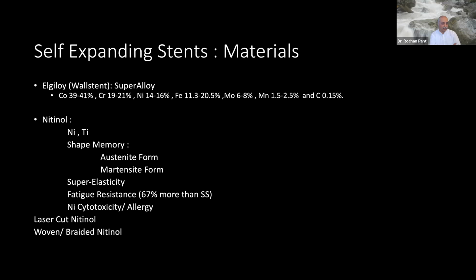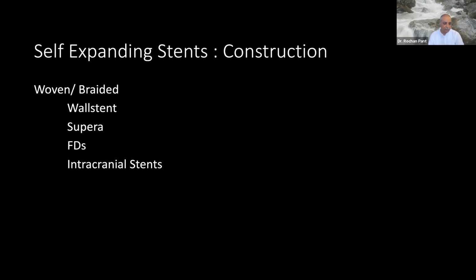It has a lot of fatigue resistance as compared to stainless steel. So you'll notice nitinol wires are far more resistant to changing the curve and shape as compared to stainless steel wires. But of course, they contain nickel. So nickel cytotoxicity and allergy are both things that can happen with the material. Woven braided nitinol has now become very popular for making stents like, say, the Supera, or a wide variety of stents meant for use in the neurovascular circulation, which will not be the primary focus of this talk because the talk would stretch forever and more if we got to every kind of stent that exists. So basically, we have discussed the materials for bare metal balloon expanding stents and self-expanding stents.